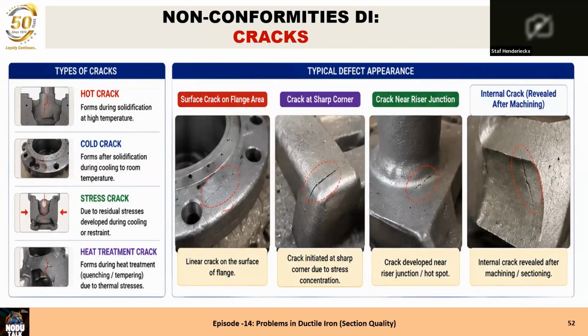When you see it over there in a flange, it's a hot crack over there. Somewhere it happens there when there is a defect inside the casting. During the solidification, the defect acts as a crack initiator, and it can crack over there. At sharp corners, of course, you can have it there, and it can be lack of shrinkage possibility, or at the moment it becomes just solidified.